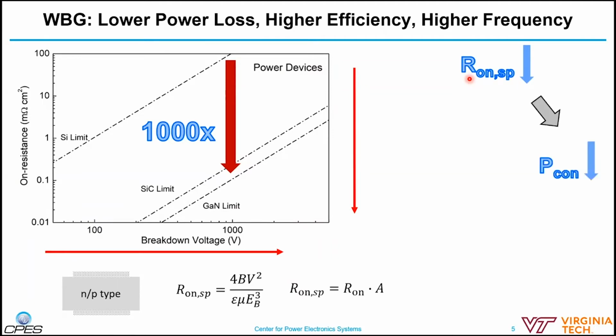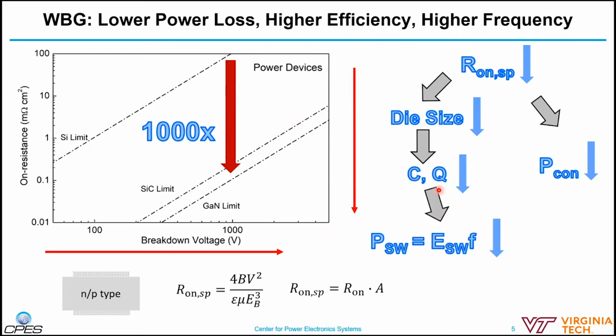On one hand, if we make the devices with the same die size, the on resistance will be much smaller, and when conducting a certain current, the conduction loss will be smaller. Or the other way is that if we want to build devices with the same on resistance, then the lower specific on resistance means the die size will be much smaller, which means the capacitance and the switching charges will be much smaller. That means that when we switch this device once, turning on or off, the total energy loss will be much smaller. As a result, the device can switch at a much higher frequency, and it can also allow much lower power loss.